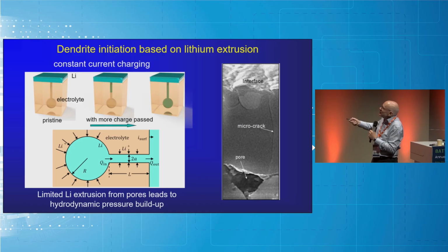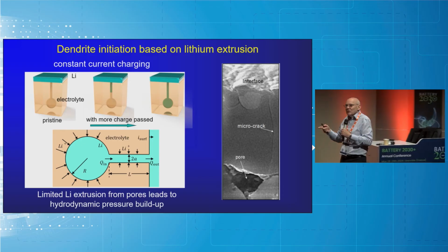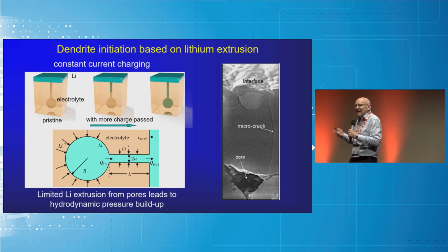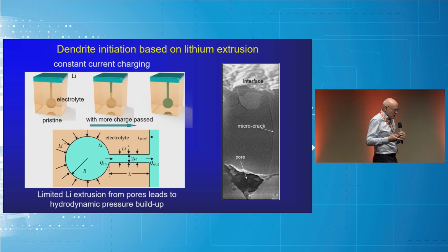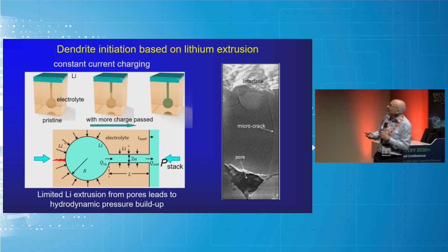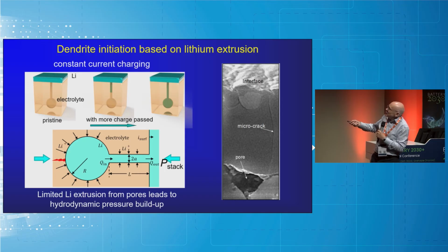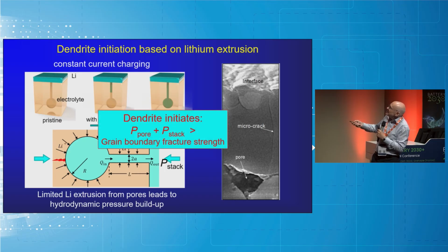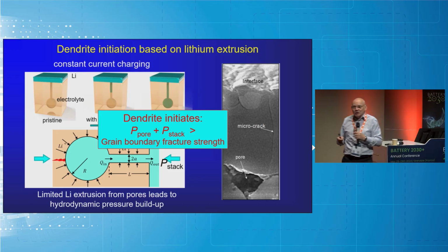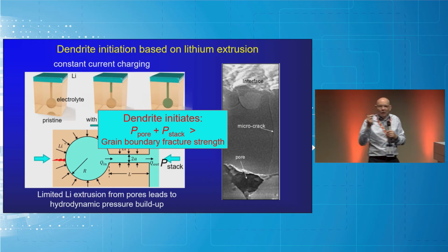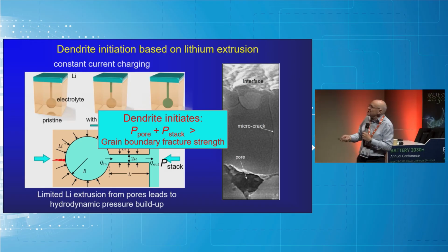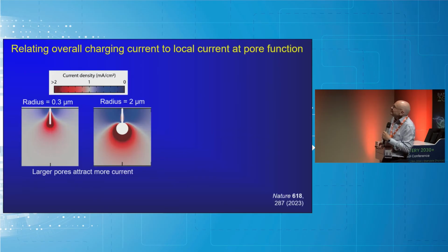So that builds pressure in here. So if you're plating at a high enough rate that you're forcing lithium in here faster than it can get out, pressure will build in this pore. It was always a bit of a mystery how a soft metal could crack a hard ceramic. But it's not the mechanics, it's the flow processes of lithium that are doing that. And once you reach a certain pressure, you will initiate a crack. And that is basically when the pore pressure, forget the stack pressure, is greater than the grain boundary fracture strength. The energy, if you like, that's holding the grains together at the grain boundaries. Once that's exceeded in the pore, you'll get a crack.